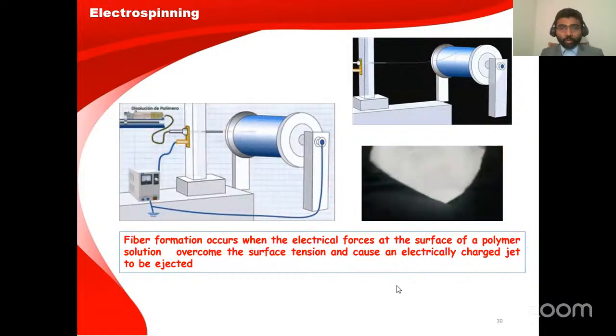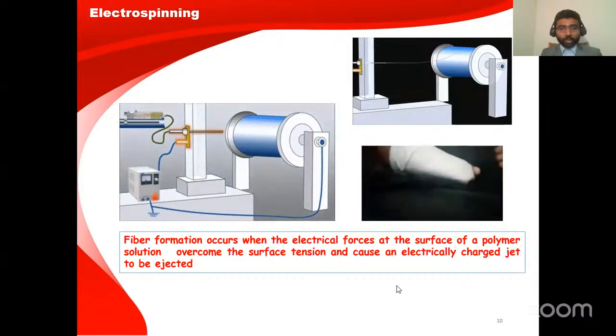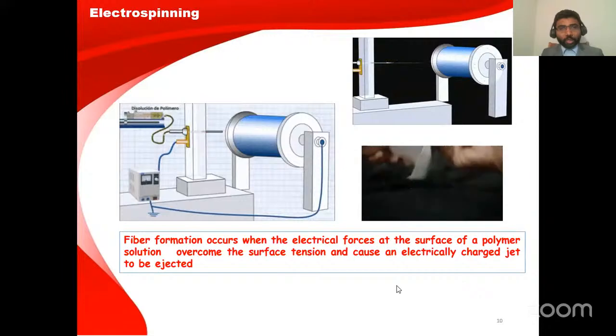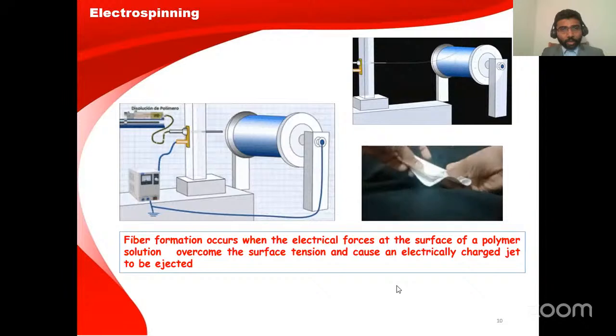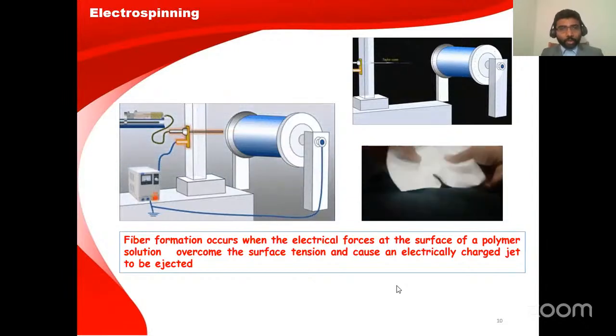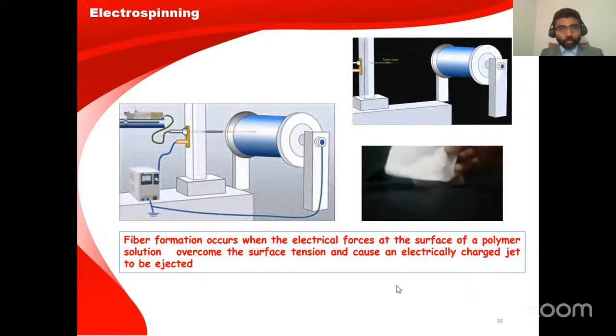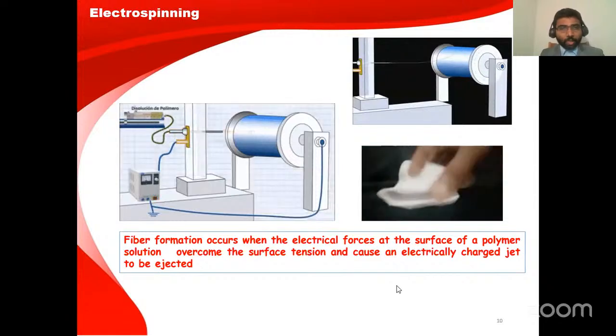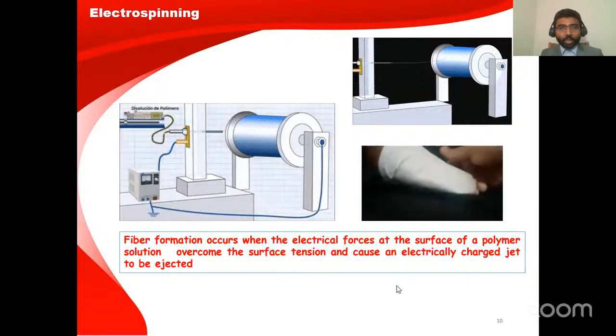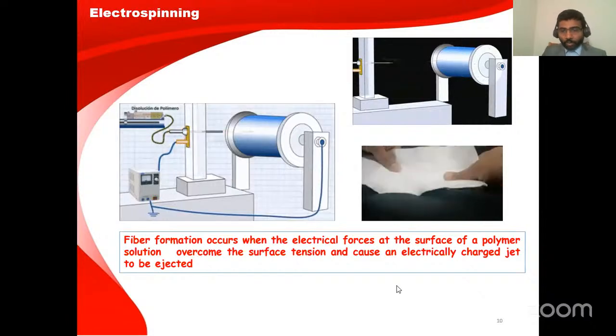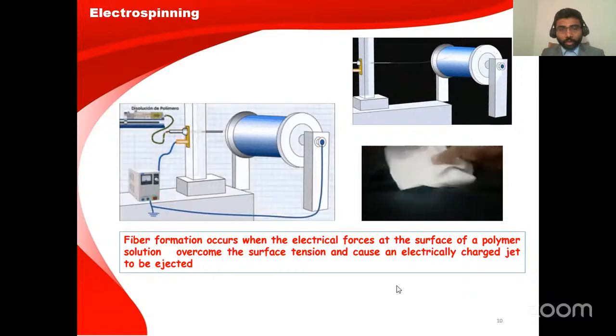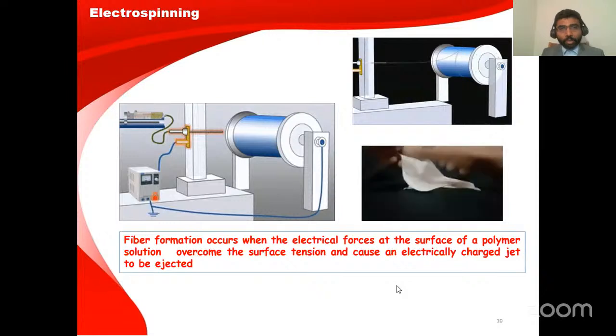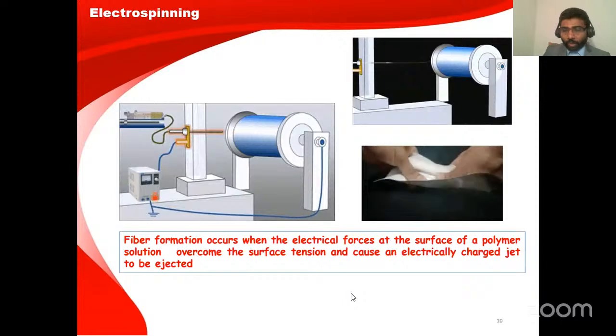These are very excellent for skin substitute application, wound dressing making, etc. The technology uses a high voltage power supply to drive polymeric solutions to a collector from a syringe pump. In a syringe, we take the polymer solution and apply high voltage like 15 kilovolts. Due to this high voltage, the polymer will be charged, and when we apply a specific flow rate using a syringe pump, the droplets come out from the needle tip and move towards the collector because of the electric charge inside the polymer. And we will collect this on the drum collector or a flat collector, which should be a metallic plate or metallic drum, from where we can peel it out and take it like that. You can see how flexible these materials are.